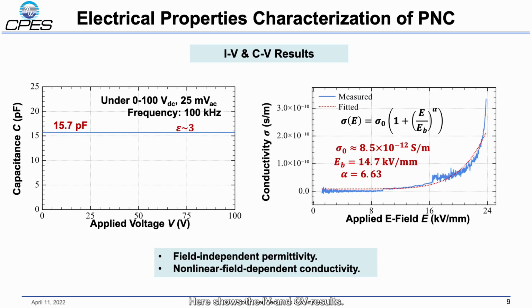Here shows the IV and CV results. So the CV test is under 0 to 100 V DC voltage with a 25 millivolt AC bias at a frequency of 100 kHz. We got a field independent capacitance, which is 15.7 picofarad. And we can use the formula we showed in the last slide to calculate the permittivity. It's about 3. And then we use the IV curve to